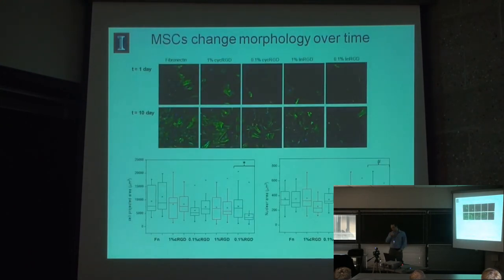And one of the things that was interesting with these experiments, and I started thinking about when I was considering some of Adam Engler and Dennis Discher's work, is the morphological changes that occur on these different materials. And if you put cells on gels, you'll see, as the cells can exert tractional forces differentially on these different materials, you see a similar thing here when you change the density of the ligand. Here on the cyclic peptides, most of the cells have more of a cuboidal shape, very symmetric. But as you go to lower density cyclic peptide and the high density of the linear, you start to see elongation, where cells are getting more elongated, they're taking on different shapes.